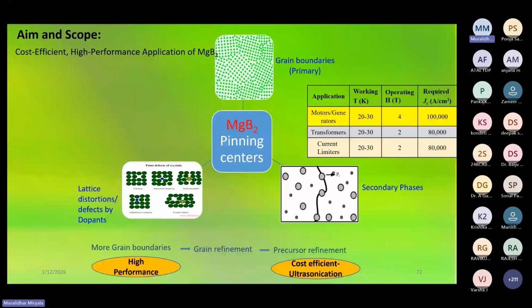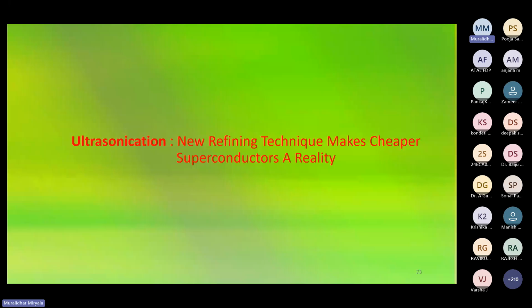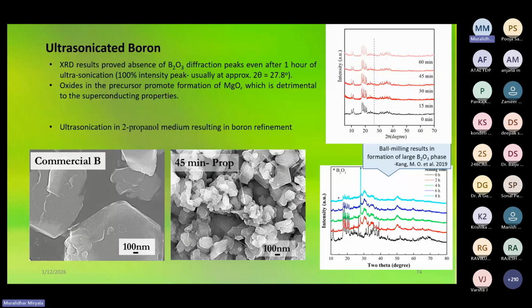So the boron size becomes smaller and smaller, and it will act as grain boundary pinning. As a result, the performance goes up. People are trying to use nano-order boron, but no one has succeeded. But we did it with ultrasonification, a new technique. This is one of the cheapest methods, and we can make large quantities of nano boron using this technique. You can see the commercial boron to nano boron. We did this in propanol for 45 minutes.